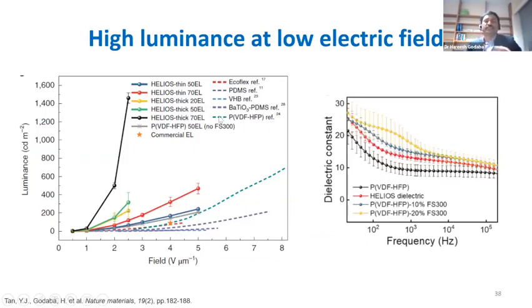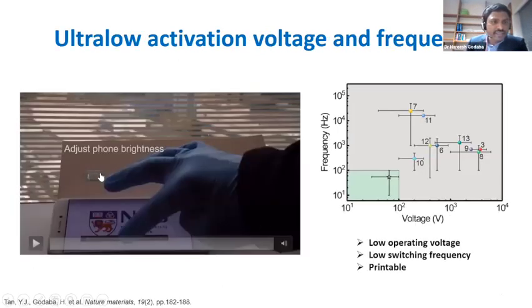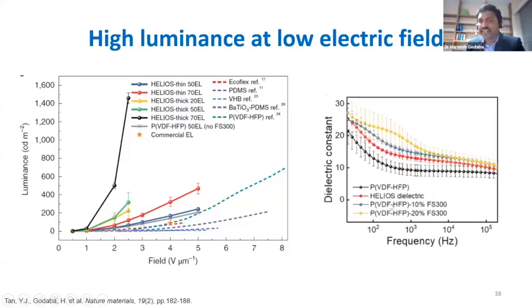Yeah, so looking at the reason for this, first, if you see on the left hand side, this Helios material's luminescence is far higher than most of the other electroluminescent materials that are described in literature. So the reason is this Ecoflex EL, which I've shown here as a control group. For example, this material has a dielectric permittivity less than 3. But for this Helios, once we have this PVDF mixed with FS300, we actually see that the dielectric permittivity can be more than 20, or even more than 10 in the high frequency region, which basically increases the charge carrying capacity so much, and this helps to achieve a high luminescence. So the improved dielectric constant is a key reason for this.